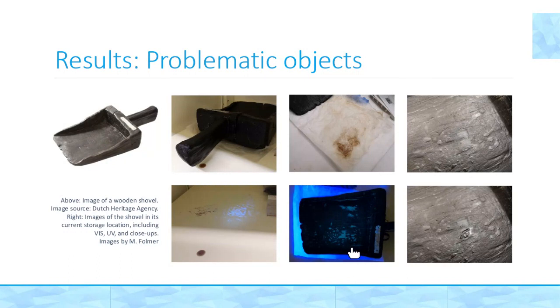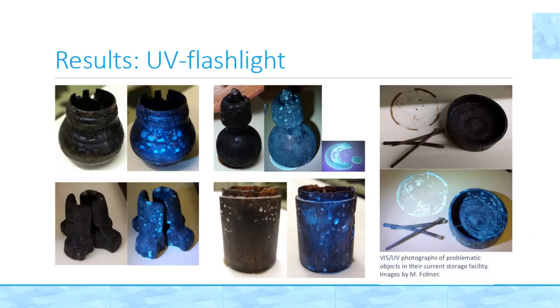Then on the right, my scientific curiosity got the best of me and I poked one of the pools. Instead of being hard and solid like I expected it to be, the surface felt soft and it actually showed a shimmering, wet-looking, sticky surface underneath, as you can see here. I then looked for more similarly treated objects, and interestingly enough, they all showed very similar problems.